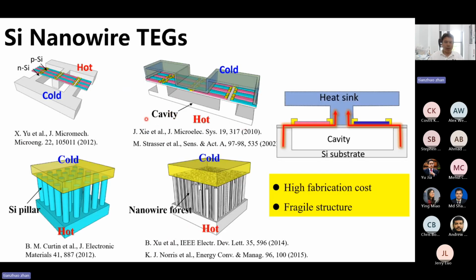Since then, various silicon nanowire TEGs have been developed, including the planar type and also the vertical type. For both types of silicon nanowire TEGs, we need to etch the materials surrounding the silicon nanowire to cut off the heat flow path, in order to form an efficient temperature difference. But this process results in some problems. For example, it has a very high fabrication cost, and also a fragile structure.